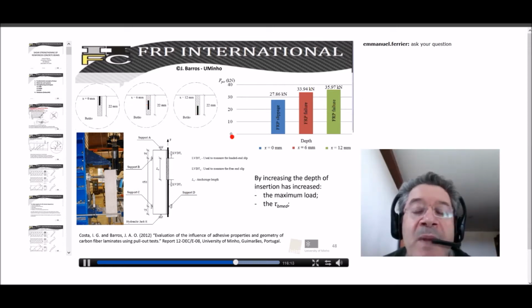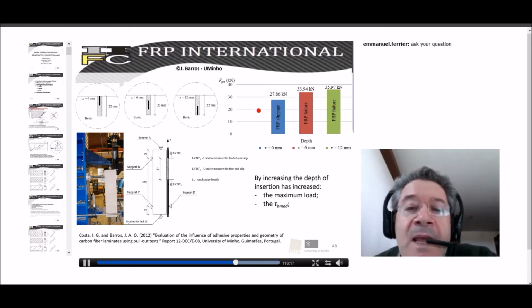Look at the results that we obtained. We have a clear indication that when we install the laminate deeper in the groove, the maximum pull-out force increases. The blue corresponds to the results when we install the laminate at the surface of the groove, and the green corresponds to the situation where we install the laminates deeper in the slit. So this means that it is a good idea to install the laminates deeper in the groove. Of course, we are limited by the concrete cover thickness, but in general, we have a concrete cover thickness that is 20, 25, or even 30 millimeter.